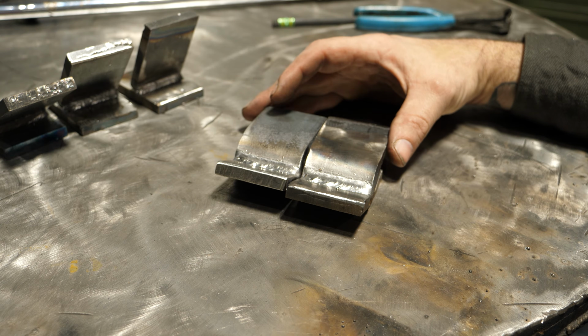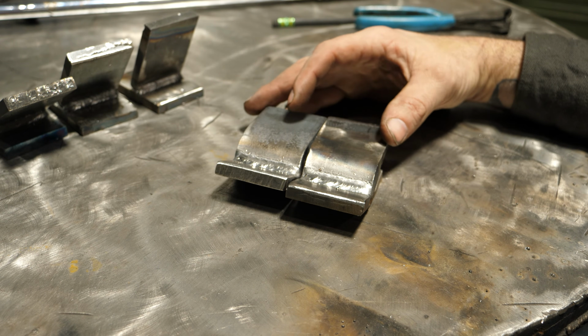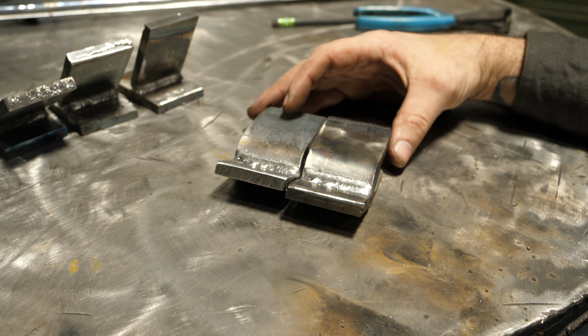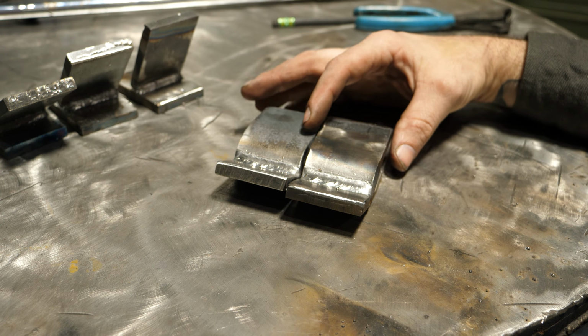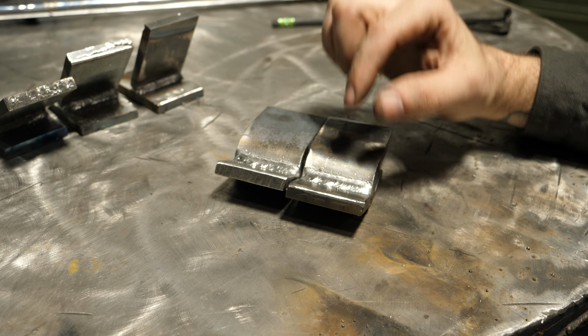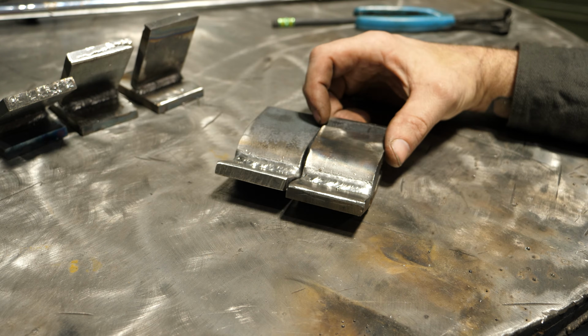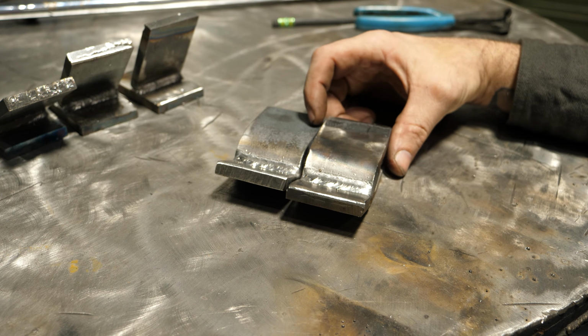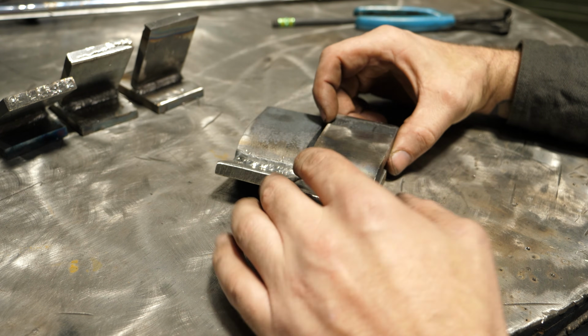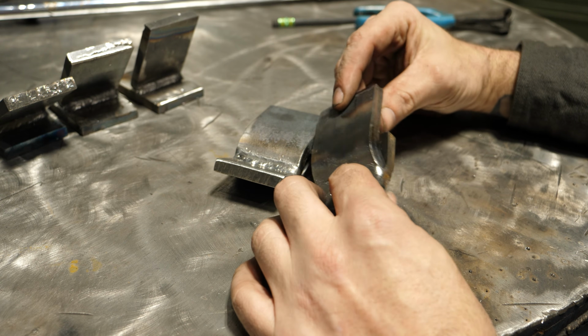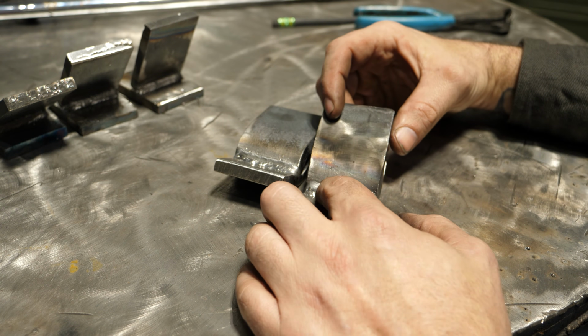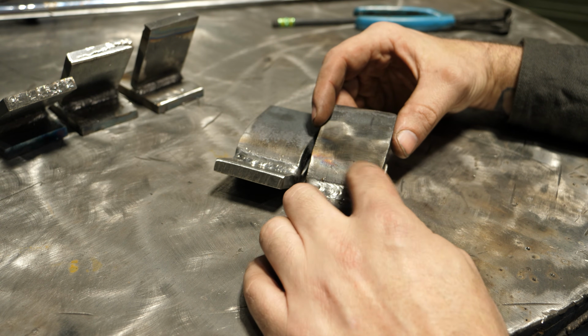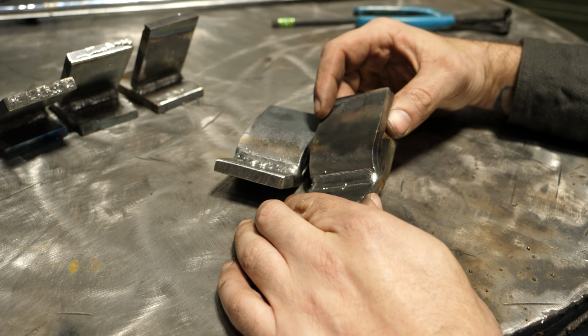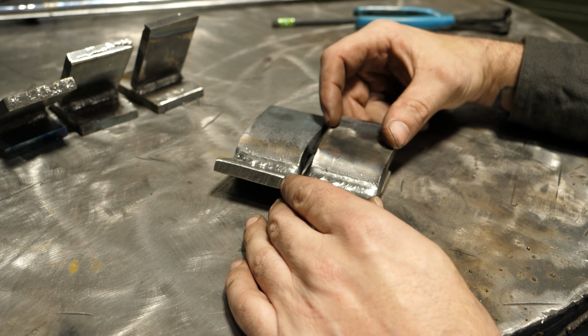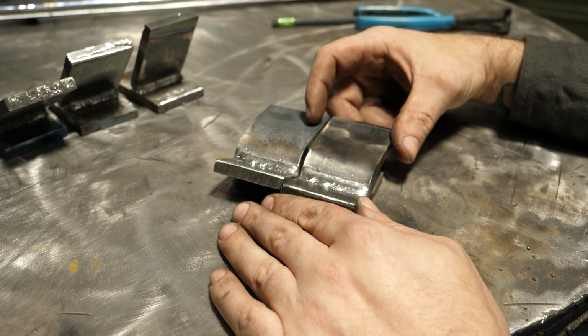Well, both of these, the preheated plate as well as the non-heated plate, passed bending away from the face. I mean, for a single pass weld done with short arc MIG, which doesn't really have the greatest penetration, to have both of these pass with essentially an undersized weld. That weld is not proper size for this 3/8 plate. That's pretty cool that they both did. I would not have bet that. I didn't think either one of them would.